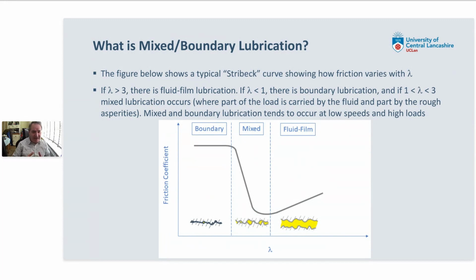Then as the lambda ratio increases, as we increase the film thickness, we'll start getting some of the load carried by the fluid and some by the asperities. And so because some of the load is carried by the fluid, the friction coefficient drops from its value in the boundary regime, and it will drop and drop until the amount carried by the fluid is 100% and there's none carried by the asperities. So on the right hand side of this figure, the fluid is thick enough to completely separate the rough surfaces, and the friction is entirely determined by the properties of the fluid, things like viscosity. If we carry on increasing the value of lambda, we make the film thicker and thicker, the friction actually goes up because you've got to overcome all the friction of carrying this big thick fluid film.